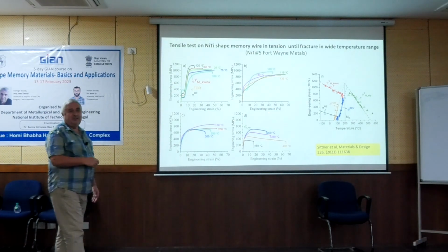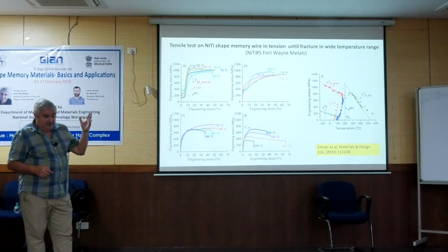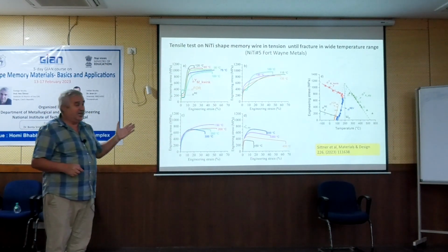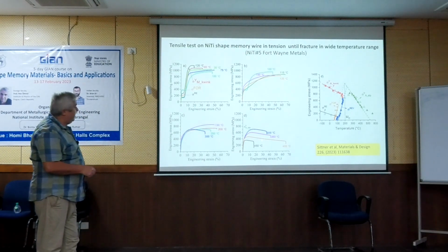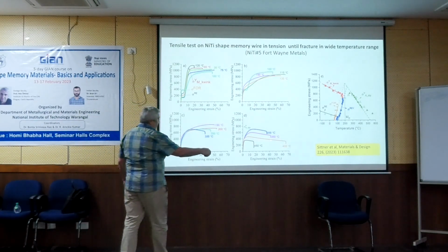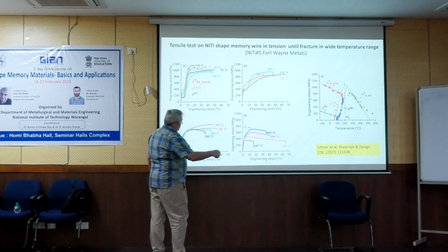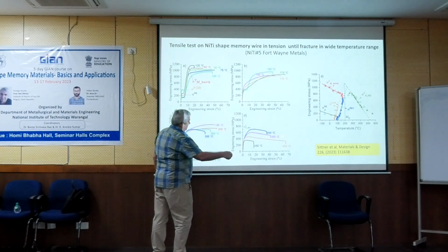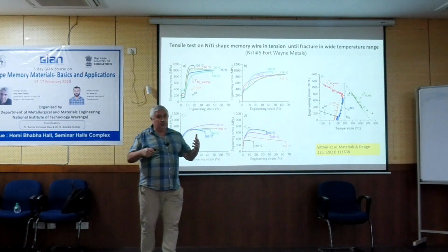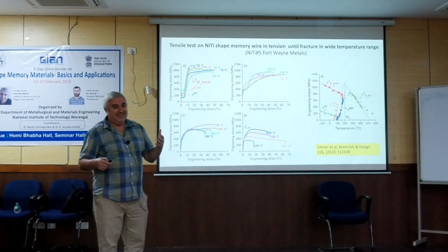One interesting point: some postdoc was working on it, a lady from Russia, and she used the DMA to measure these kinds of curves. When she used the DMA, these curves at maybe 400 Celsius started here, then were flat, and then it fractures. So it was completely different in DMA. In DMA, you use force control. You prescribe the force. Do you understand why it was different?